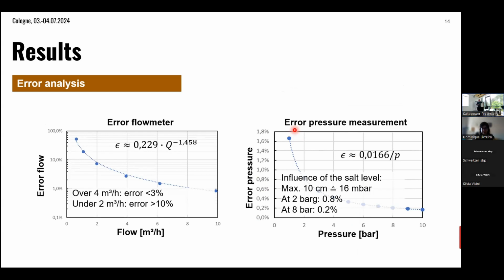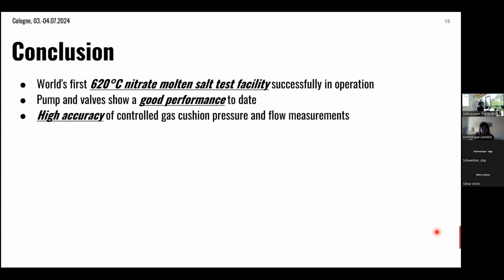So the last slide is about the error analysis. I checked how accurate our flow measurement is, and also how accurate our pressure measurement is. We see that especially for the low flow under 2 cubic meters per hour, we have more than 10% inaccuracy. However, if we have a higher flow above 4 cubic meters per hour, the accuracy is okay. For the pressure measurements, we actually have quite high accuracies. For the high flows, it's below 0.2%.